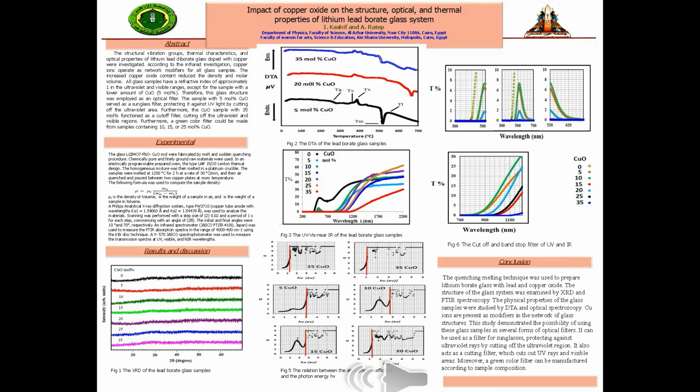The samples were measured by density, FTIR, XRD, and UV-visible spectrophotometer. Figure 1 shows the amorphous nature of the glass with no peaks. The measured DTA shown in figure 2 allows the values of Tg, Tc, and Tm to be determined from the curve. It can be noted that the single value of Tg represents the greater homogeneity of the glass sample.